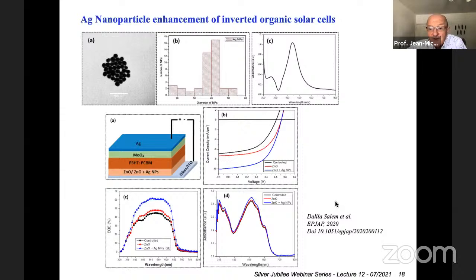So in order to use wisely the nanoparticles, we incorporated them into the electron transport layer, because there, into the electron transport layer, they can just conduct because they are conductors, so it cannot do a lot of damage to the photovoltaic efficiency. But interestingly, they scatter the light. And we see scattering by this absorption spectrum figured here, in which we see that the absorption spectrum looks reinforced under the presence of the nanoparticles, which is the blue curve here. So the control layer is just the composition poly 3-hexylthiophene PCBM, which is a fullerene, a derivative of a fullerene.